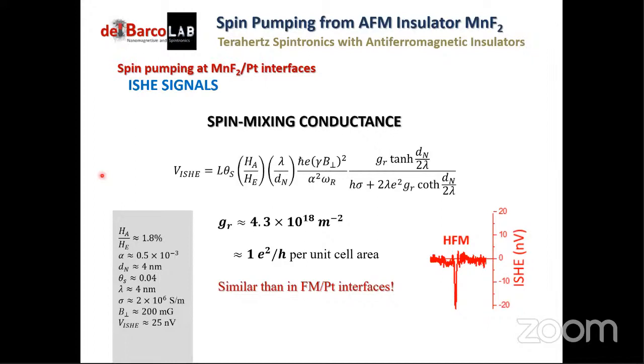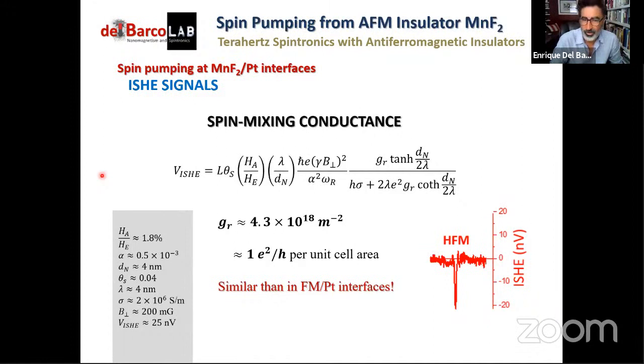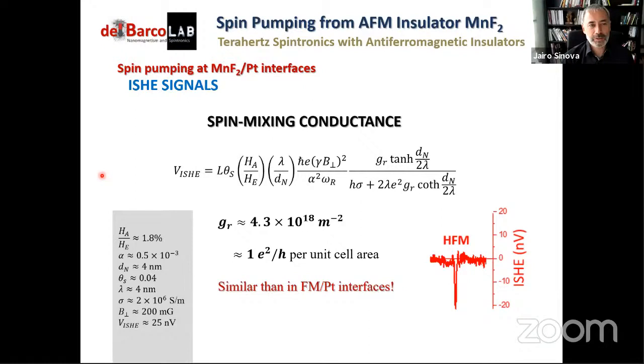Well, my understanding is that at the interface, there's not a big difference if you just look at the interface when it comes down to spin transfer between two materials. Definitively, you need conduction electrons to move, but those will be in platinum, and this is a conductor, right? But my understanding is that the spin mixing conductance analysis works from insulator to insulator in kind of the same way, because it's effectively tunneling, right? It's a concept of tunneling.